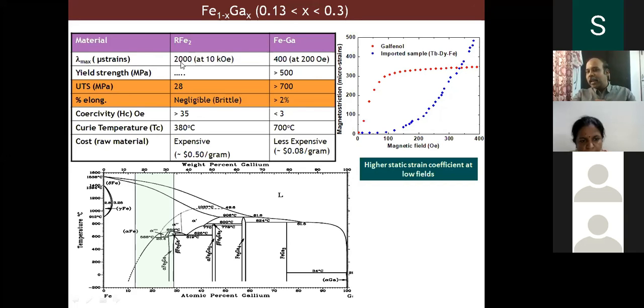The coercivities are much less because anisotropy is low. The Curie temperature is more than 700 degrees centigrade, and this is less expensive compared to this one. For example, this is $0.5 per gram. This is only $0.08 per gram. But the advantage we are supposed to get, we are getting in this one. So we have also gone for developing this material because it's more cost effective and the processing is also relatively small.